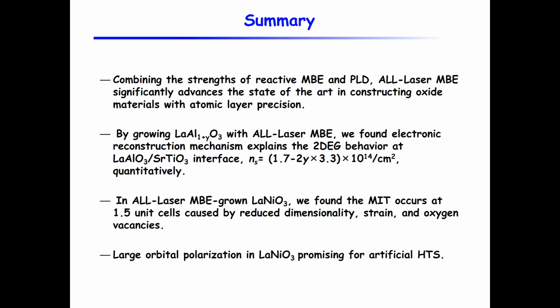And then lastly, I showed you this lanthanum nickelate work that shows that the metal insulator transition in the system is not only the result of reduced dimensionality and strain, but oxygen vacancies are also very important. And the last slide I showed is this large orbital polarization, very promising for making artificial high-TC superconductor materials.